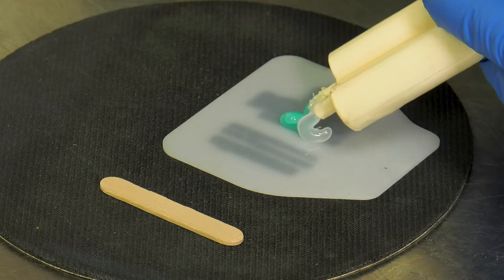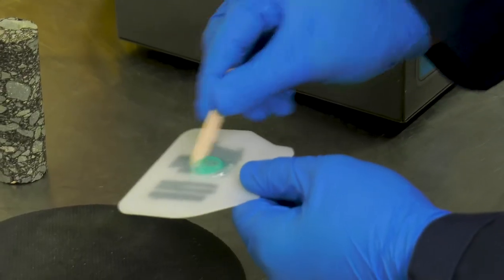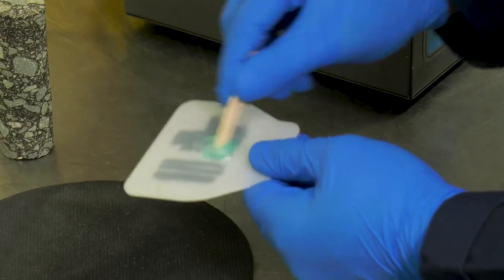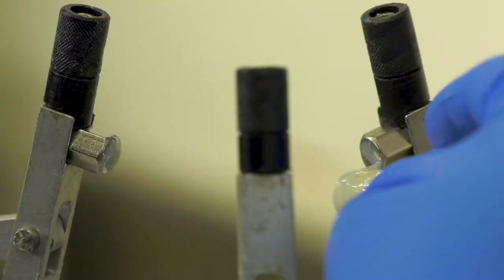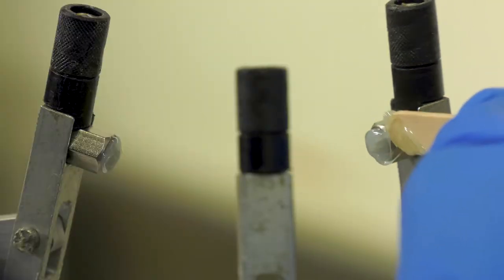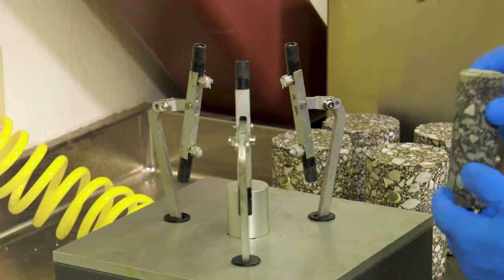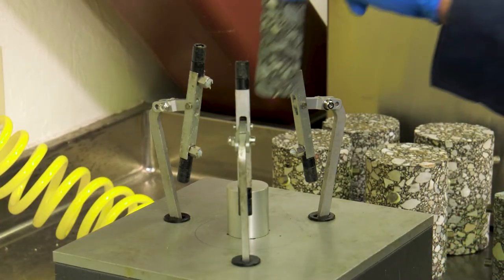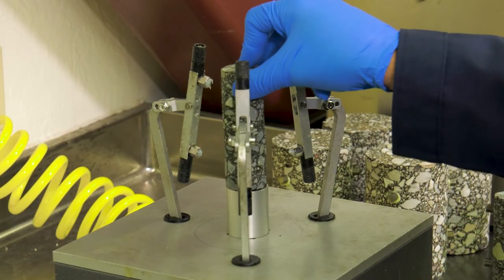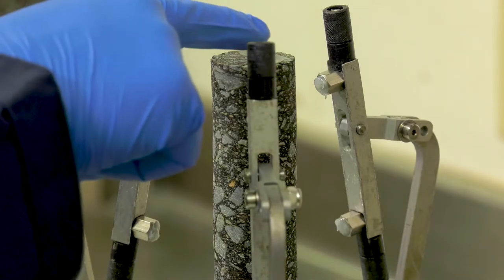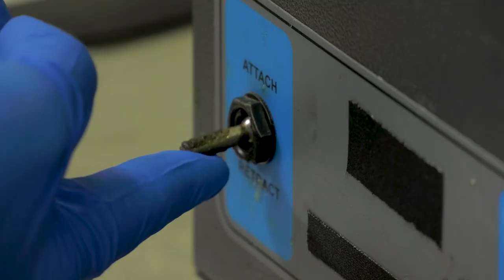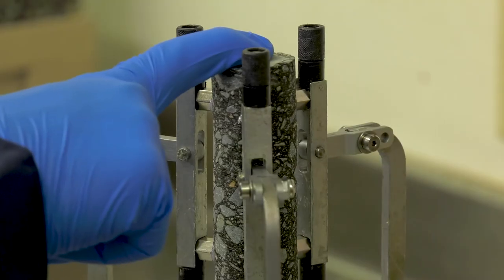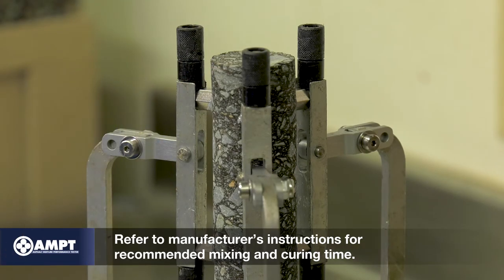Apply glue to the mixing pallet and mix thoroughly according to manufacturer's recommendations. Apply glue evenly to the installed studs. Place the specimen on the center of the stage, making sure it's aligned correctly. Gently stabilize the specimen with one hand and activate the jig to close the setting arms. Refer to the manufacturer's instructions for recommended mixing and curing time.